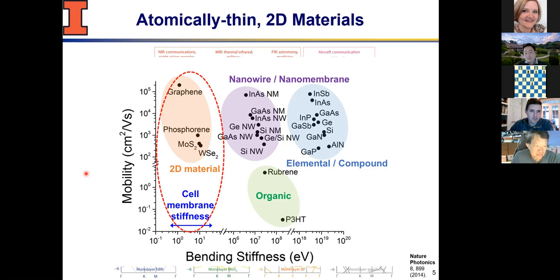And it led us to this plot that we put together, where the y-axis I'm showing here is the electron mobility or carrier mobility. It depends on the polarity of the material. That's how fast the carrier will transport in a unit electric field. So the higher it is, the faster it will transport. For electronics applications, we do want them to be fairly high, right? So there are some of these indium arsenide, gallium arsenide types of material that people are very interested in for their high mobility applications, but they're very difficult to grow and things like that. There has been lots of research interest in there, and that's where the 2D materials exist.